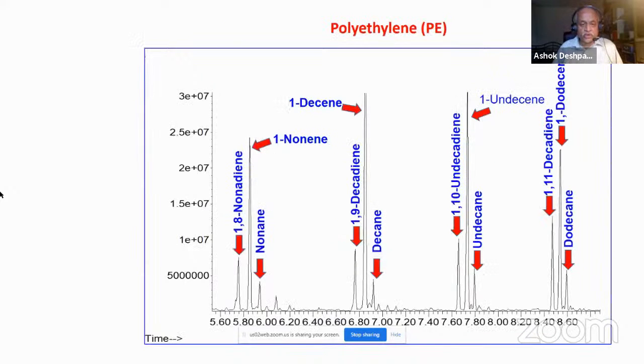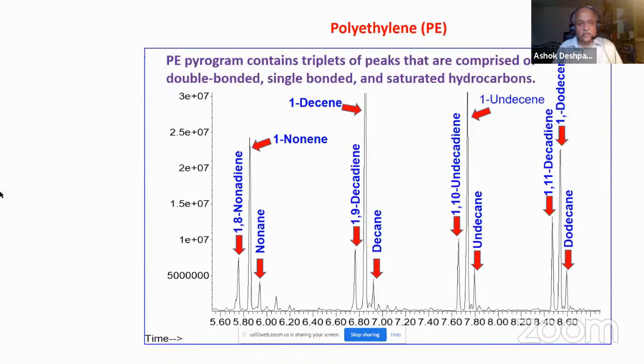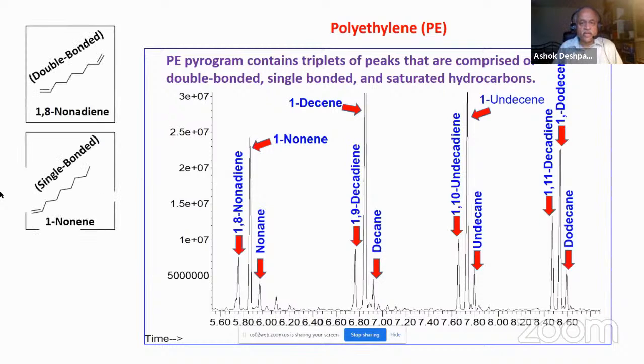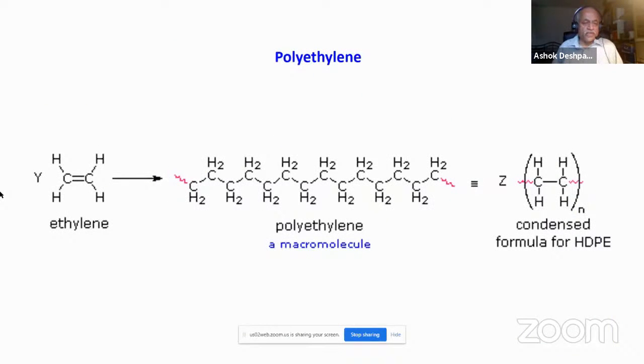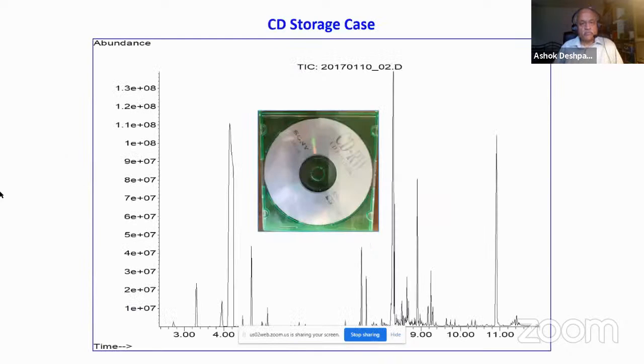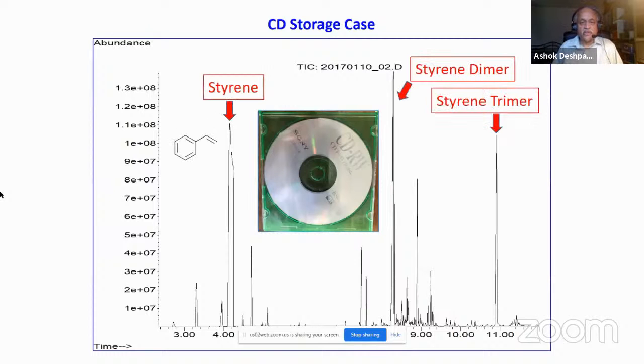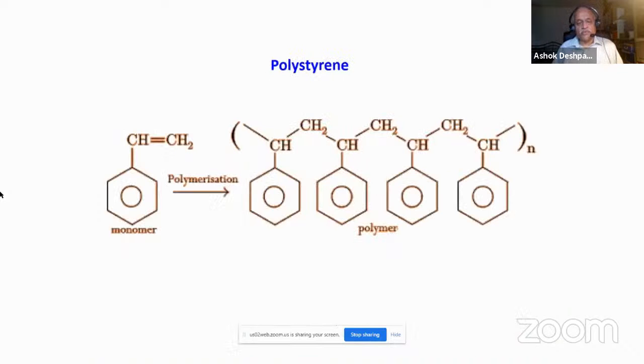This is a zoom picture of the previous chromatogram, which shows the triplets that are comprised of double bonded, single bonded, and saturated hydrocarbons. Again, ethylene molecules polymerize to form polyethylene. The CD storage case has marker peaks of styrene, so we call it polystyrene. When styrene molecules polymerize, it forms polystyrene.